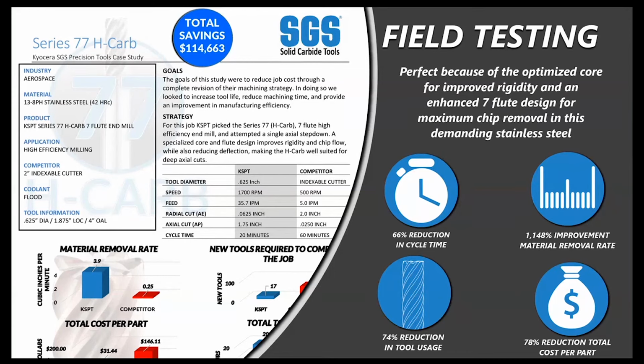While the tool cost for the H-carb was significantly higher than the indexable inserts, we went from 15 to 60 parts per tool. Our material removal rate also jumped from 0.25 to 3.9 cubic inches per minute, which brought the customer cost per part from $146 to only $31. So in the end, we saved the customer over $114,000 on this one job.